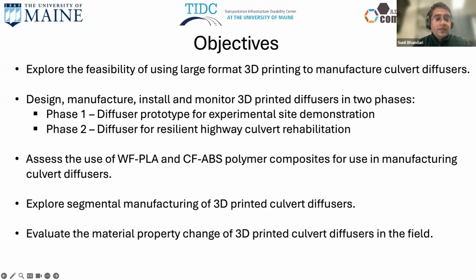We also wanted to see if we can do segmental manufacturing of the 3D printed culvert diffusers. This is important because with segmental manufacturing, we can make parts that are larger than the build envelope of the 3D printer, and it also makes it easier to transport. And we also wanted to evaluate the material property changes of 3D printed diffusers in the field. So we wanted to see how the material's mechanical properties degrade over time, and if that's acceptable for the lifespan of the structure.